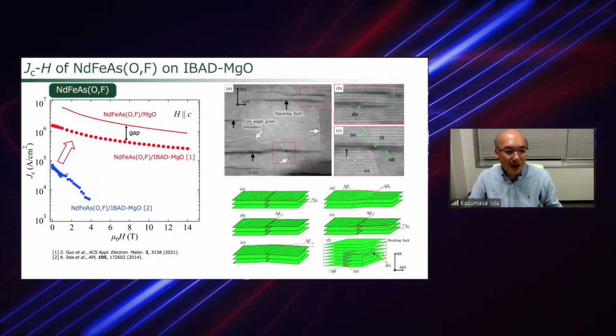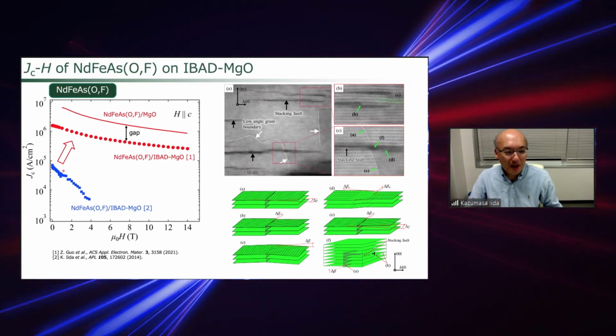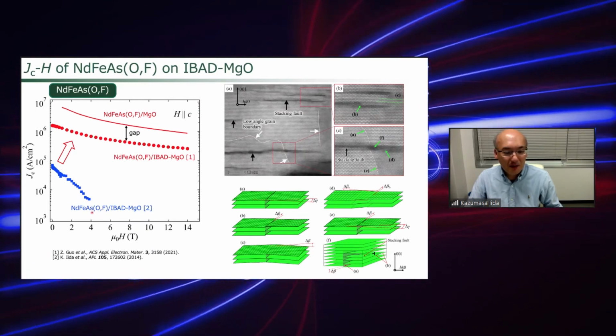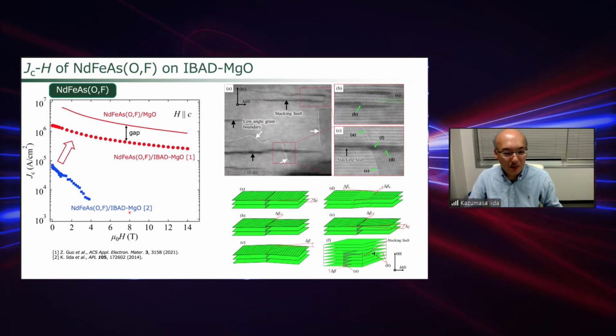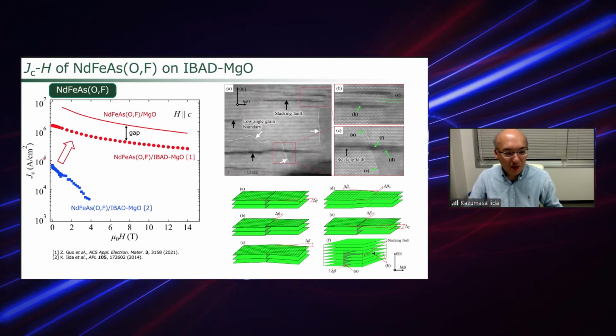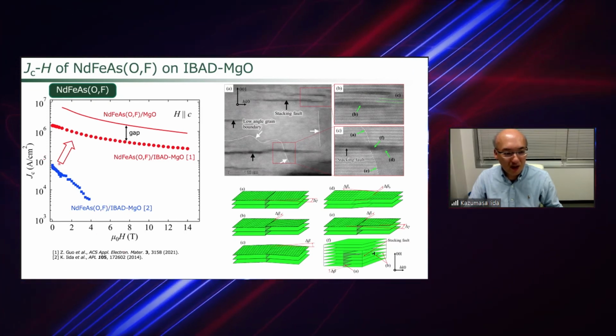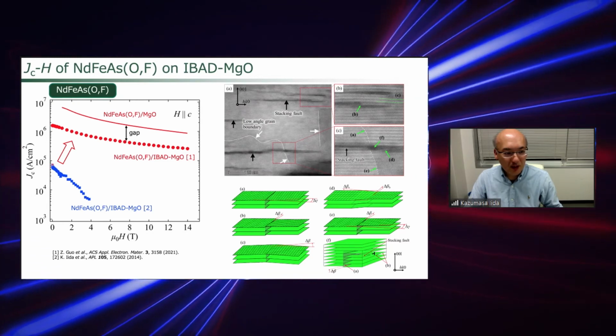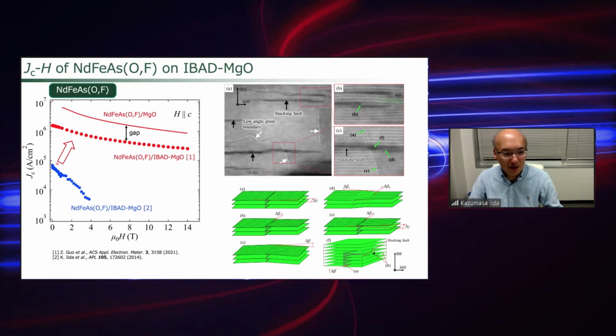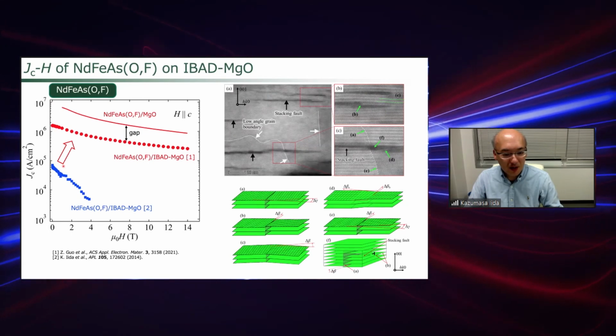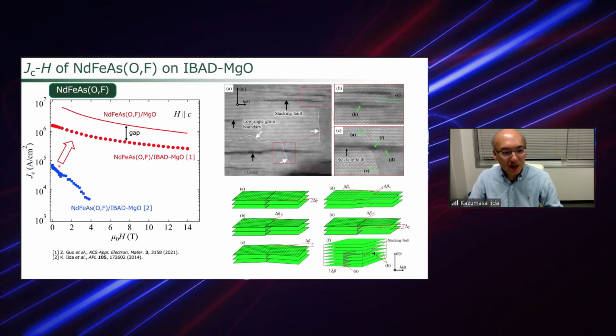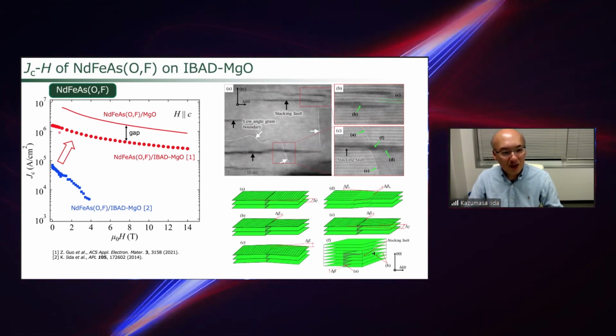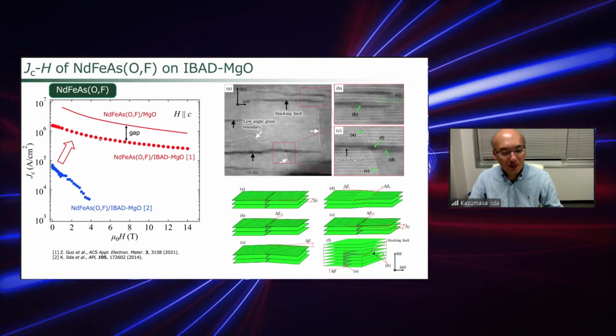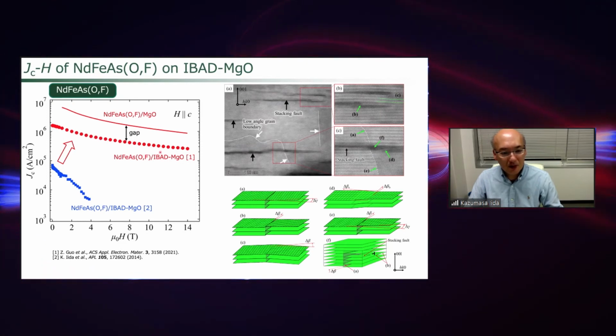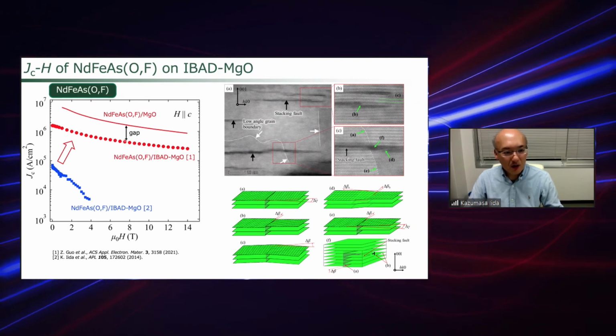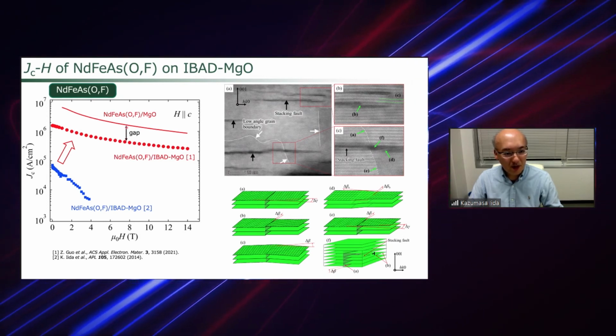And we fabricated 1111 films on the IBAD template. In 2014, we reported a Jc of below 10 to the power of 5 ampere per square centimeter. But 7 years later, we improved significantly the critical current properties of these films grown on the IBAD MgO, although the performance gap is still there.